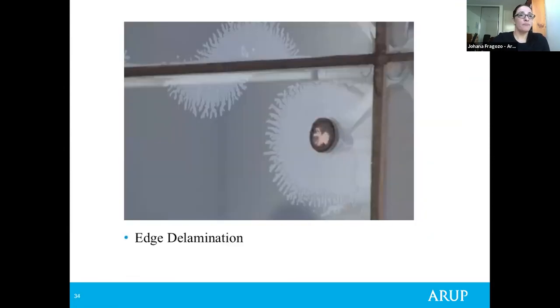With laminated glass, the most common defect is edge debonding, the debonding of the edge of the laminate. When exposed to an impact load, the glass breaks very quickly, and in laminated glass the interlayer holds these fragile panes of glass together. Hence the bond between the supporting structure and the edge of the glass, and between the glass and the interlayer, is crucial to ensure that this breakage behavior is achieved. The delamination of laminated glass usually occurs along the edges or around fixings, such as the one shown in this photo, and is most prevalent where a PVB interlayer is used.